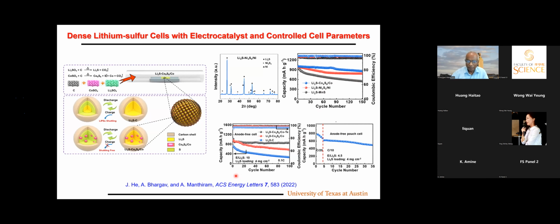And then I'm comparing here three cases, only Li2S and carbon, no catalyst. That's the cyclability. You see here, if you add this kind of reaction, you make the red curve. And then if you add tellurium into that, that stabilizes the lithium. So the black curve is the best, where we have catalyst to have better redox. At the same time, we also have tellurium to stabilize the lithium plating and stripping to get the best cyclability.